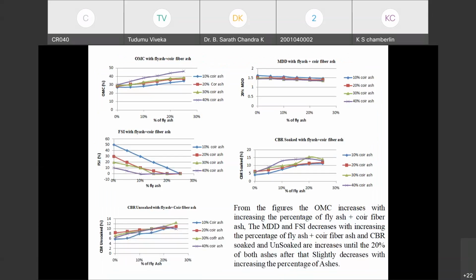From these graphs, the OMC increases with increasing percentage of fly ash plus coir fiber ash. The MDD and free swell index decrease with increasing percentage of fly ash plus coir fiber ash, and CBR soaked and unsoaked increase until 20% of both ashes. After that, it slightly decreases with increasing percentage of the additives.